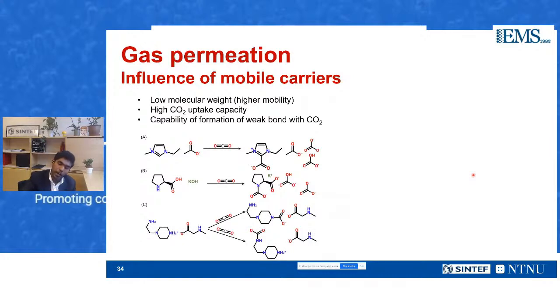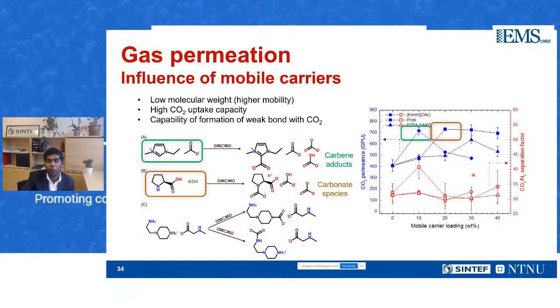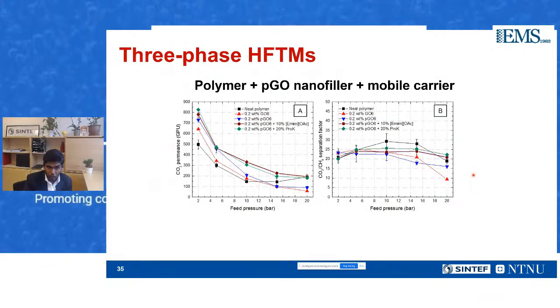So we did not stop there. We wanted to make the system even better. So we used mobile carriers, which are basically small molecules that have high affinity towards CO2. In this case, we took an amino acid, an ionic liquid, 2 amino acid salts and 1 ionic liquid. And we found that the species which form carbamate adducts perform much better than the ones which are not forming them, which are carbonate species.